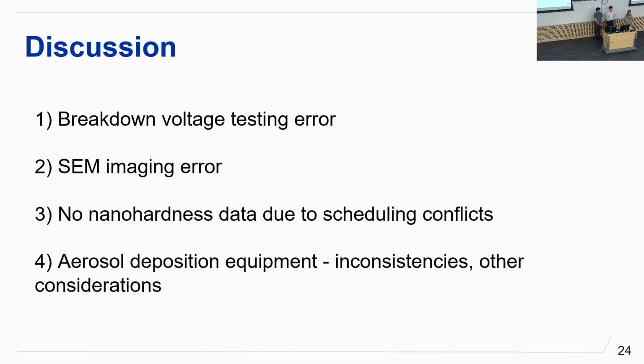So a little bit of discussion. There were some errors in our methodology that we could have introduced. For breakdown voltage testing, we were only able to test one sample because testing breakdown voltage is a destructive process, so we couldn't actually test one coating multiple times. It's also known that the approximate dielectric strength of YOF should be around 25 kilovolts per millimeter, and some of the values we got were much higher than that. So there was something with our method that probably introduced some error.